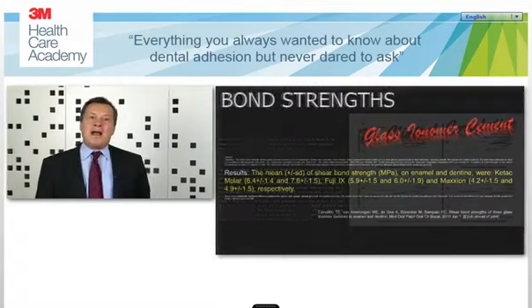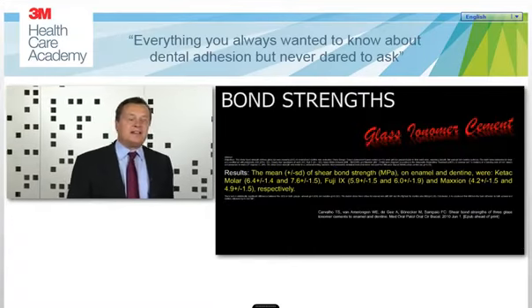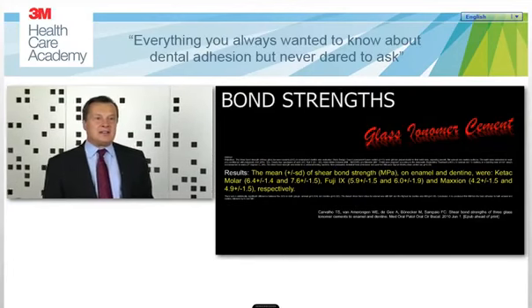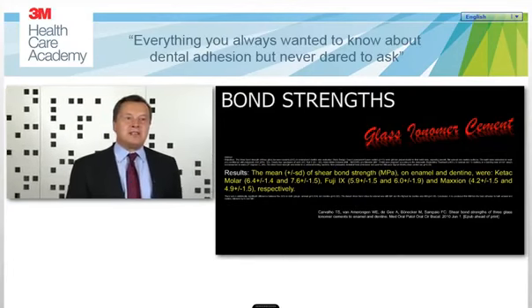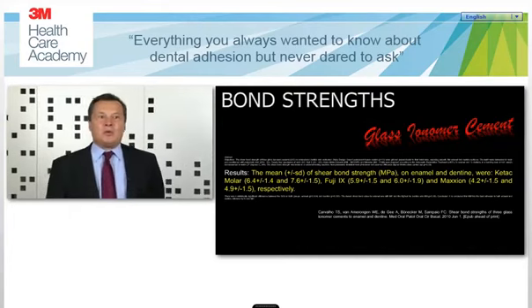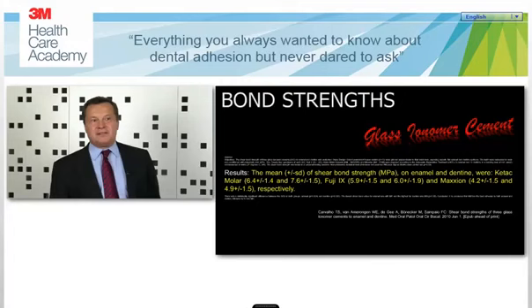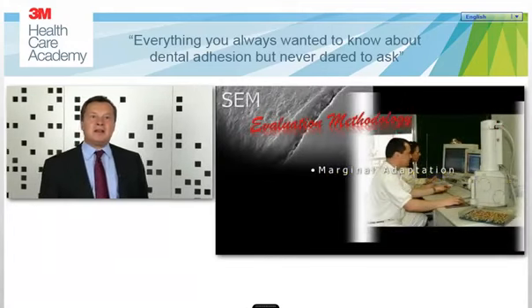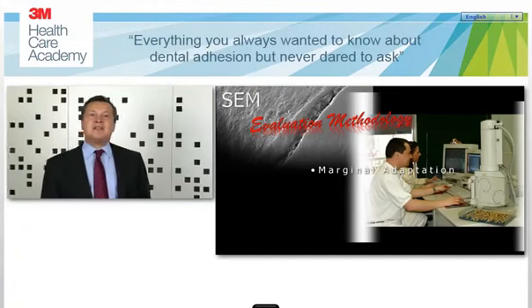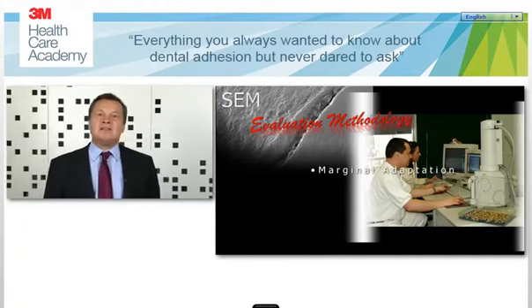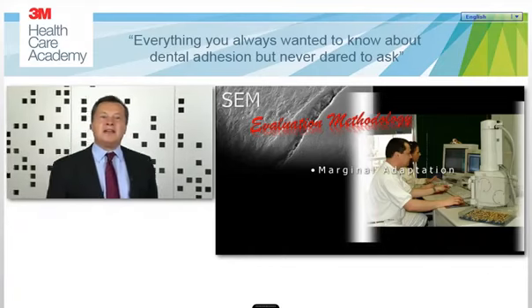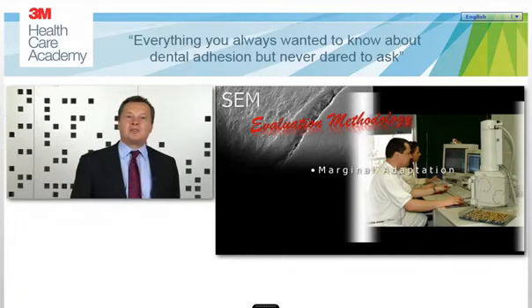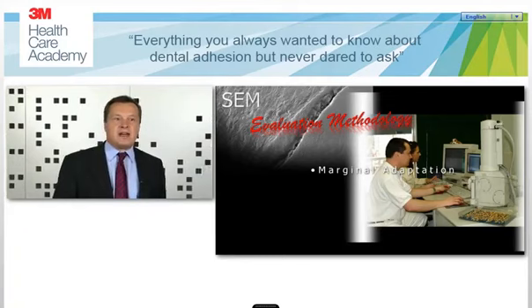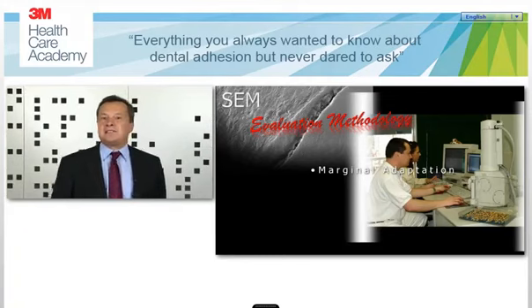To explain why this correlation between bond strength and clinical behavior is not really relevant, I would like to show you this slide, which represents a study on the bond strength of glass ionomer cements. In fact, glass ionomer cements behave very, very well in class 5 cavities, so there is enough retention of these glass ionomer restorations, even in the long term in the clinical situation. On the other hand, the bond strengths of glass ionomers are much, much weaker than bond strengths of adhesive systems. Glass ionomers have bond strengths of about 5, 6, 7 megapascals. Adhesive systems have bond strengths of maybe 15, 20, 25 megapascals.